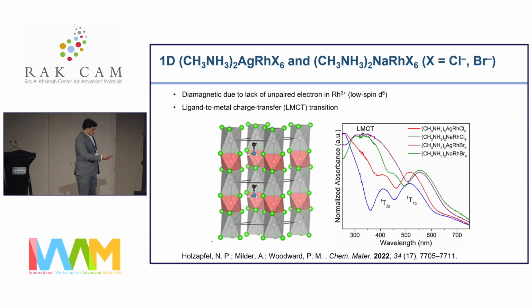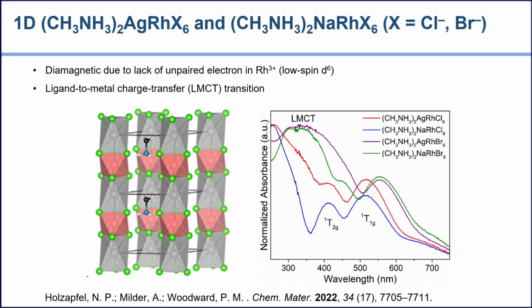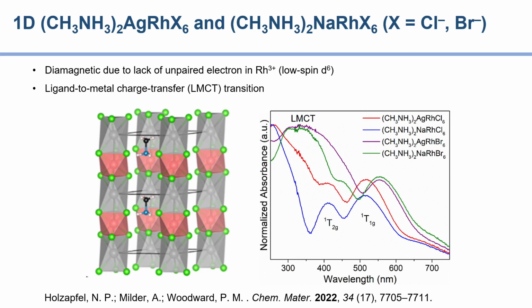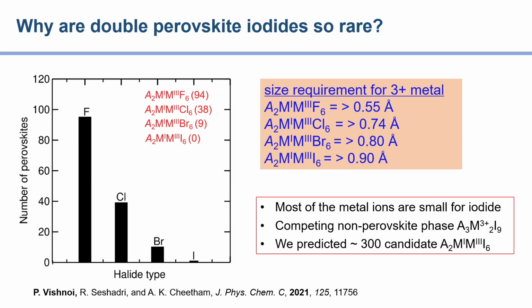So moving forward, I'll be talking about some more structures based on the model that we designed, whether you're going to get 1D or you're going to get 3D. One of the papers, which came out about a year and a half ago from Pat Woodward's group, suggests that if you calculate these parameters for a composition, here it is a rhodium-based system, which is the right side neighbor of ruthenium. It's non-magnetic, of course, because of the d6 electrons, which are paired. But its tolerance factor and radius ratio are perfect for the 1D structure that we laid out. And all these 4 compounds are actually one-dimensional structures, similar to what we obtained for ruthenium. So that further validates our model on the 1D system.